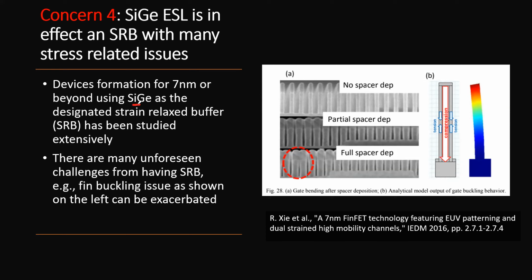And this is similar to what we saw here, just not that complex. This is very simple, our ESL layer, and their stress relief buffer is very complex. But it does not matter. From that process, we learn a lot that has been studied extensively, especially stress-related issues. For example, they found out that because of the dummy gate formation, they are sitting on a strained buffer, right? You have a strain relief buffer underneath, so this fin has a higher tendency to tilt. Once you tilt, you're dead, right?